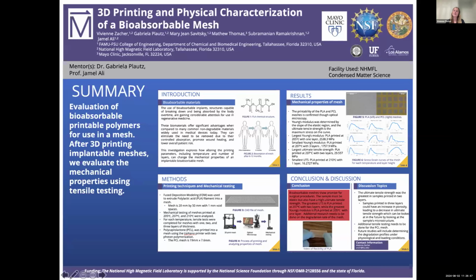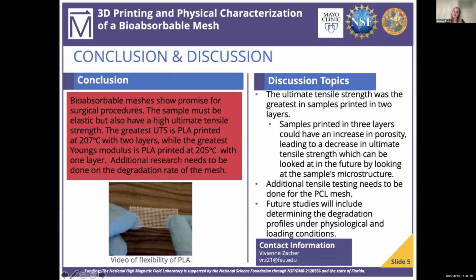we found the greatest UTS was PLA printed at 207 degrees Celsius with 2 layers, and the greatest Young's modulus to be PLA printed at 205 degrees Celsius with 1 layer. And we want to do additional research for the degradation profiles under physiological and loading conditions. And then also I plan to continue this work during the semester and give an updated presentation at the Biomedical Engineering Society Conference in Baltimore, Maryland.